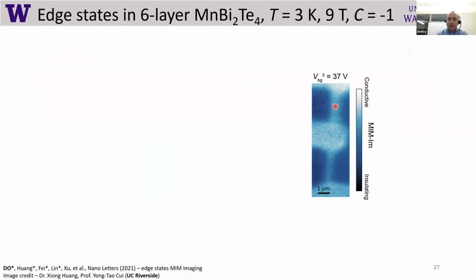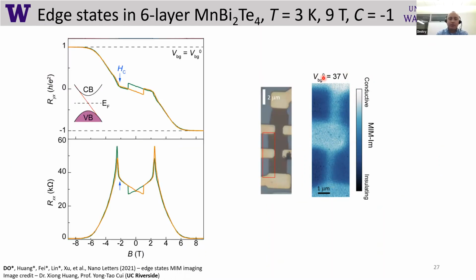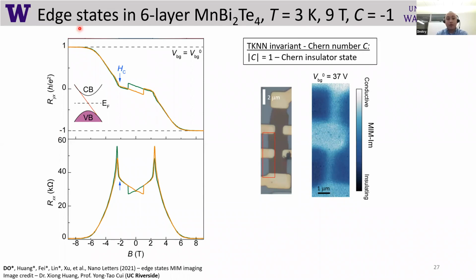So in this case, for example, at 37 volts, if we take this sample and perform transport measurements, we can see the Chern number at high magnetic field is indeed 1. So Rxy reaches h over e squared. So not only can we see this edge state, we can also confirm that this edge state is a chiral edge state with Chern number 1. So there is exactly one chiral edge state moving there.